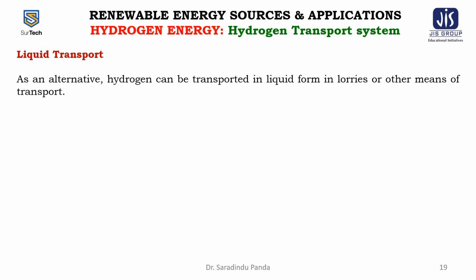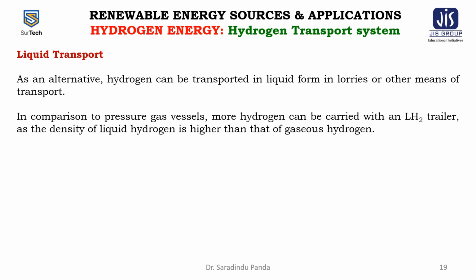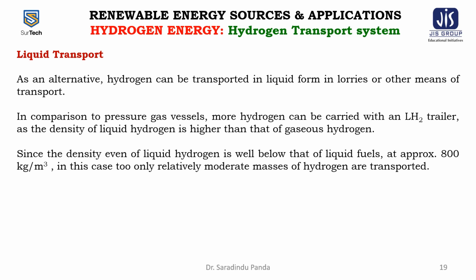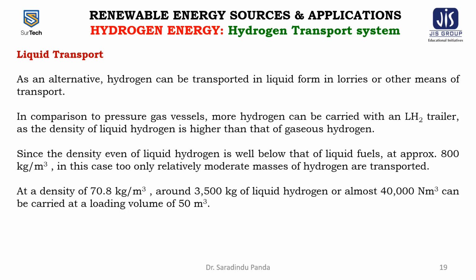Liquid transport. As an alternative, hydrogen can be transported in liquid form in lorries or other means of transport. In comparison to pressure gas vessels, more hydrogen can be carried with an LH2 trailer, as the density of liquid hydrogen is higher than that of gaseous hydrogen. The density even of liquid hydrogen is well below that of liquid fuels, which is approximately 800 kg per cubic meter. In this case, too, relatively moderate masses of hydrogen are transported. At a density of 70.8 kg per cubic meter, around 3,500 kg of liquid hydrogen, or almost 40,000 normal cubic meters, can be carried at a loading volume of 50 cubic meters.